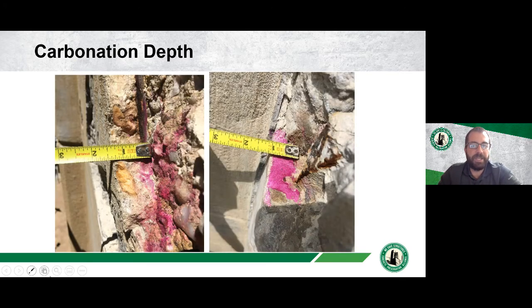But the real main issue is carbonation of the concrete. You can see here where the pH is high, but then the pH is low here, and then this is a rebar that's corroding. And so carbonation was occurring in different areas of the structure. And the carbonation was actually very spotty.